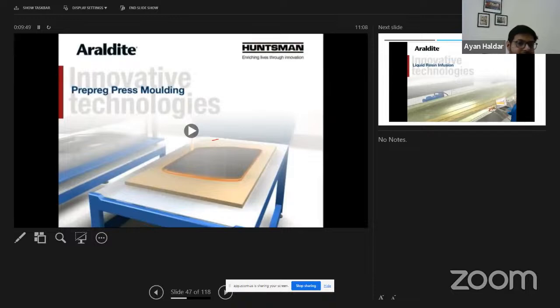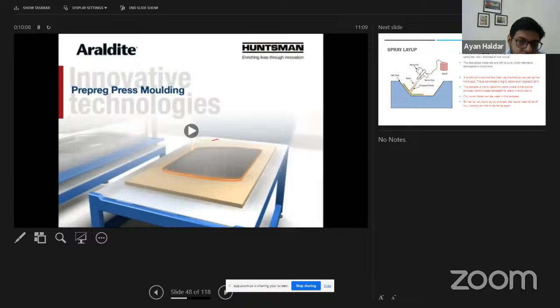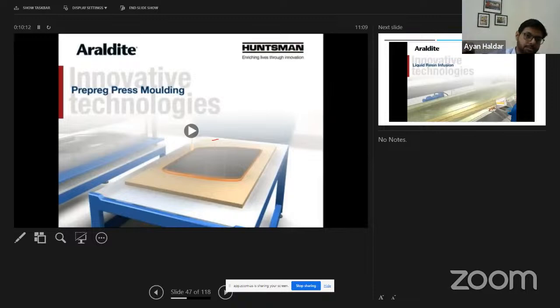Another method is called resin infusion. It's a bit different from the vacuum that we already discussed. This is called vacuum assisted resin infusion. Here also we use vacuum, but it's a bit different from what we did earlier. At that time we created the vacuum to make a uniform surface. In this case, we create a vacuum so that your resin flows automatically. Once the vacuum is created and all the air has been taken out, there is a pressure difference, and as a result your resin flows from outside to inside the lamina. And here you can make really complex shapes, and your voids will be very low, because you're creating a vacuum and allowing the resin to move inside.